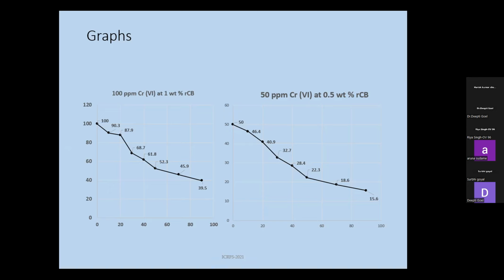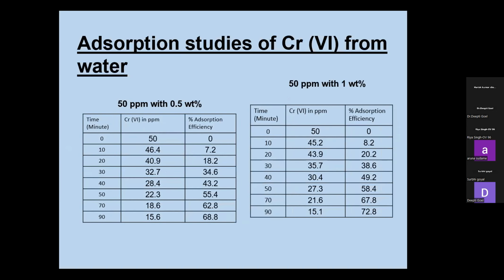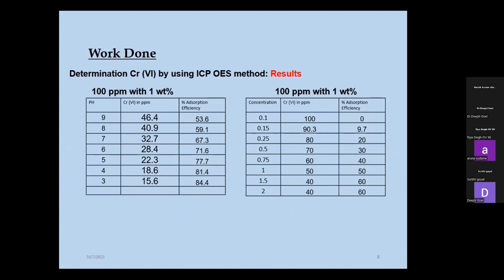So this is a graph. Here we can see how the adsorption can be seen. Now again, this is with the 50 ppm. I took different concentrations. So with the 50 ppm, the result is very good. Here we can see around 1%, 50 ppm with 1% weight, the 72.8% result is there. And another is 100 ppm, again 100 ppm. Here we can see around 60% with the 1%. That is about the concentration.